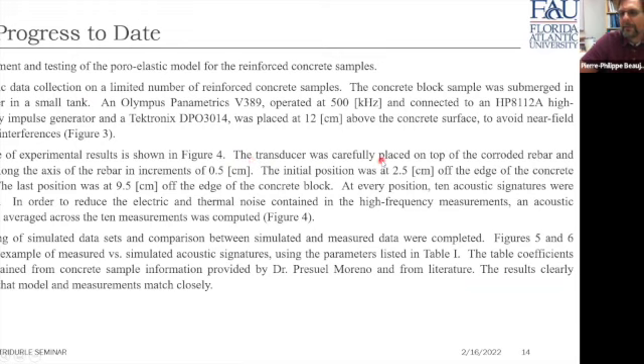Now, in that, the transducer was carefully placed on top of the corroded rebar and moved along the axis of the rebar in increments of 5 millimeters. The initial position was 2.5 centimeters off the edge of the concrete block. And I would like to mention that our position along X is measured relative to the center of the transducer. Now, the last position was at 9.5 centimeters of the edge of the concrete block.